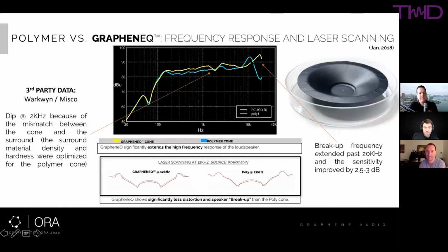The other thing we see is that we've extended the bandwidth by almost a full octave because we don't have the speaker breakup at such a low frequency. We push that up to a higher frequency, and so we get almost 3 dB more output and almost a full octave more output.